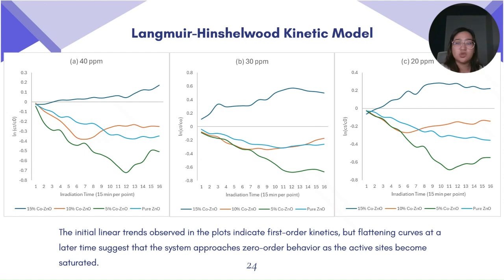The 5% co-ZnOs would start their positive slope after time point 11 or time point 12, where these data points are at the 165 and 180-minute marks of the experiment. The 10% co-ZnOs, on the other hand, would start their positive slope after time point 6 or time point 7, which means they reach their maximum degradation between 90 to 105 minutes. The positive trend in the kinetics after those specific time data points may be explained by the formation of byproducts or occurrence of secondary reactions, both of which are out of this experiment's scope of analysis.